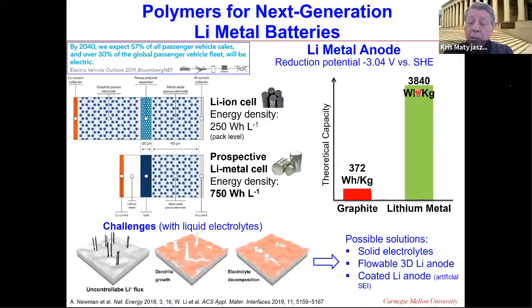But the problem with lithium metal anodes is that during the charging and discharging process, they start forming dendrites in an uncontrolled way. These dendrites grow longer and longer, and eventually they can touch the cathode and make a short circuit, and the battery would fail and sometimes may have catastrophic consequences.